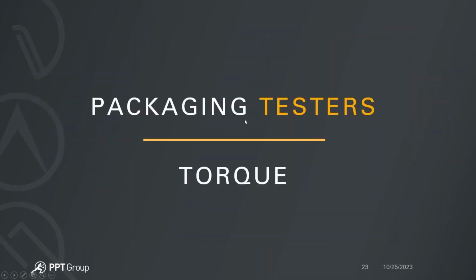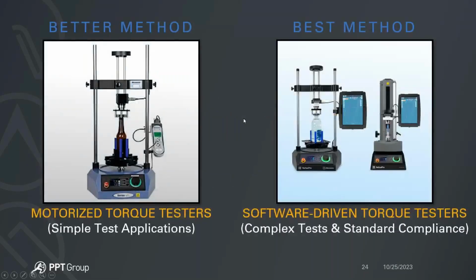The types of testers, once again, if you're a mom and pop operation running your family winery, not making much volume, you could essentially have a simple tabletop torque tester that will measure torque either in the clockwise or counterclockwise directions, which simulates application and release torque. But how fast are you turning that cap and how far are you going? If you go too far, you may be over torquing. If you don't go far enough, you may be under torquing. So to remove any of those inconsistencies or errors in the test, we recommend at least a motorized tester that takes those two important values out.